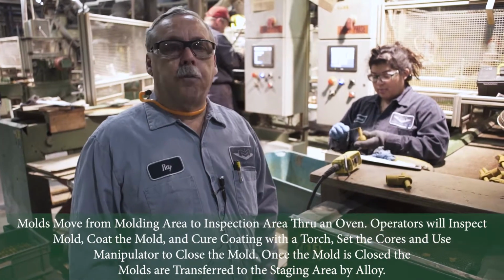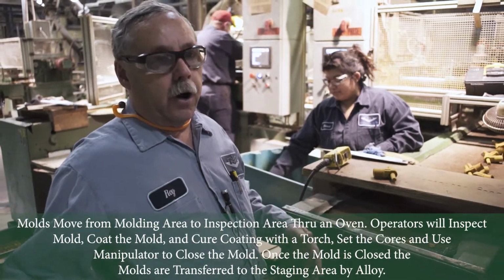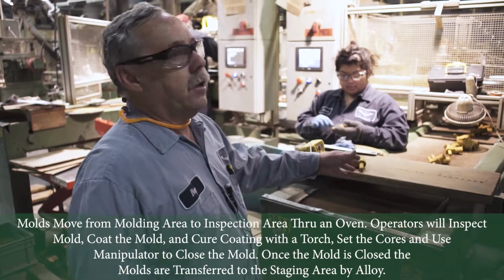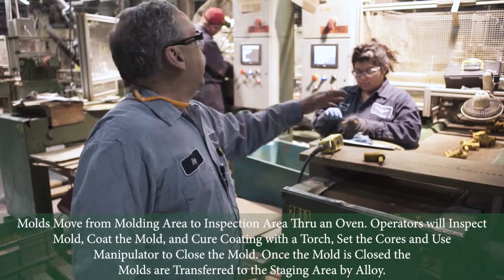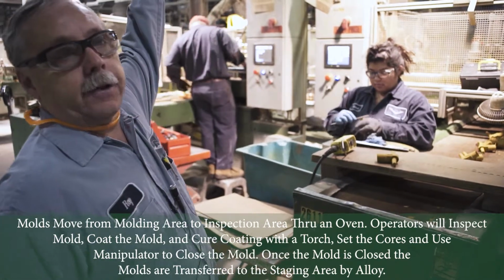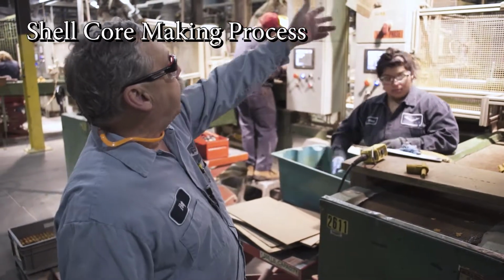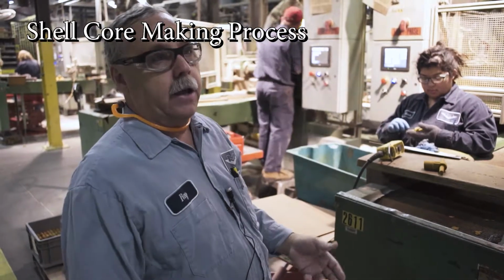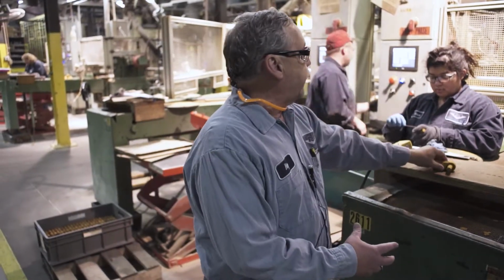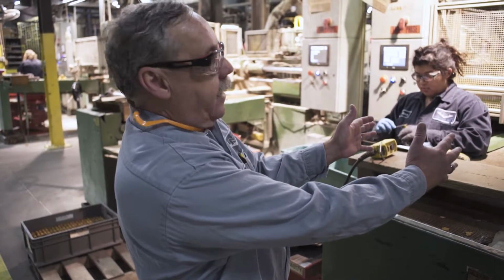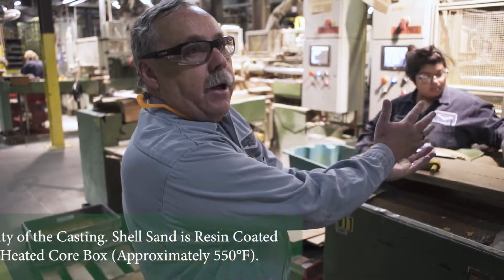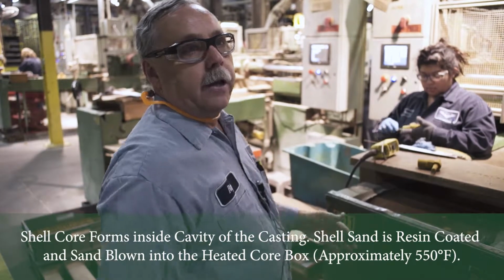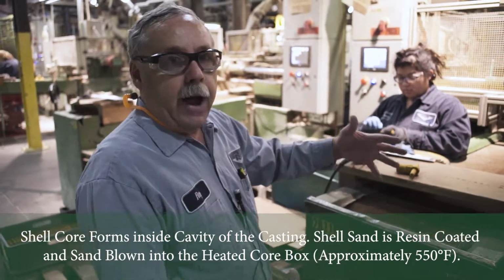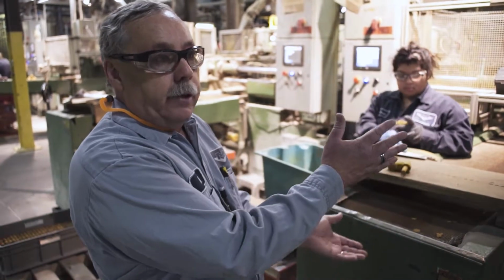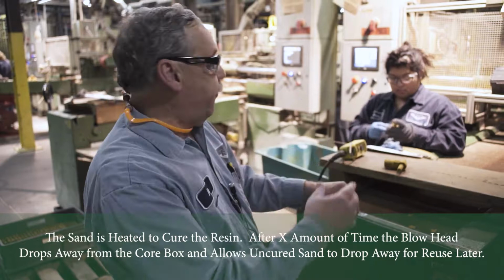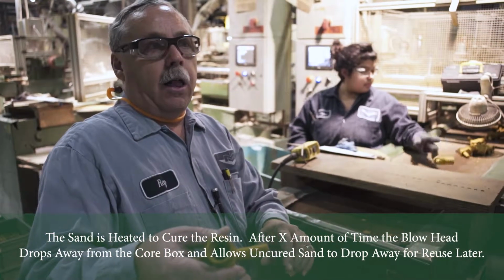We have 2 different core processes in the foundry here for the green sand line. The first process I'm going to talk about is the shell process. We get bulk sand already with resin, silica sand with resin coated onto it. We deliver it by screw conveyor and gravity to a blowing vessel. That blowing vessel will clamp up the core box, blow the sand in, and hold it clamped up under pressure. We heat it to about 550 degrees for a set amount of time. We drop the platen away and the excess sand drops out. Therefore we get what we call a shell core.